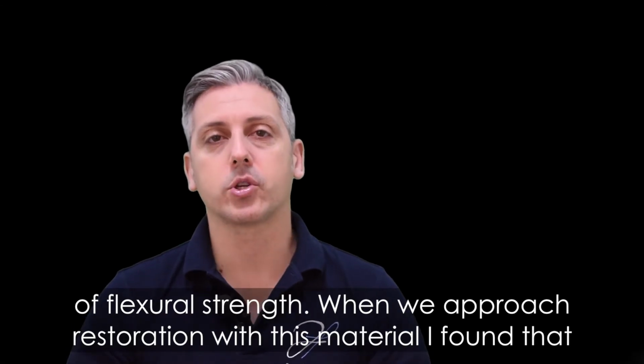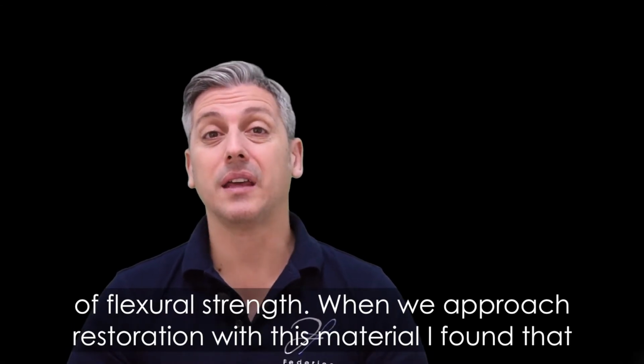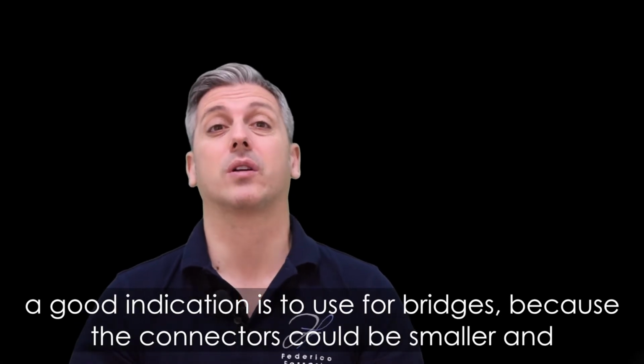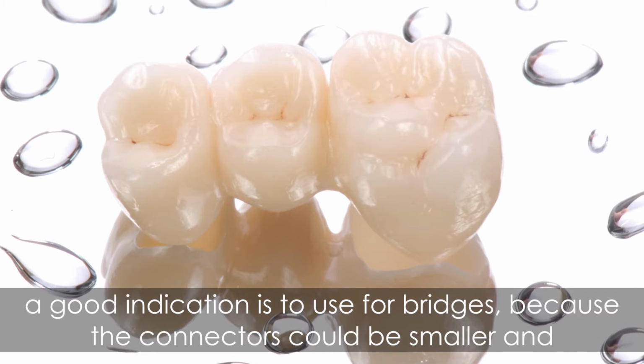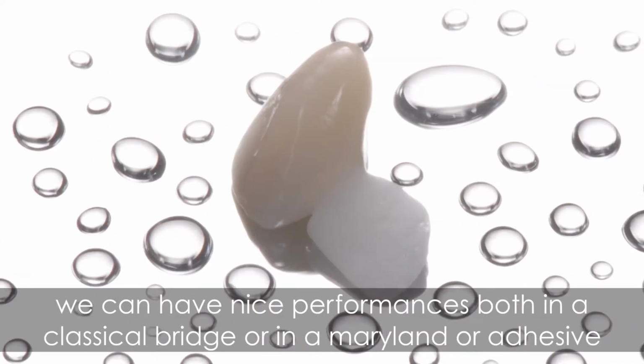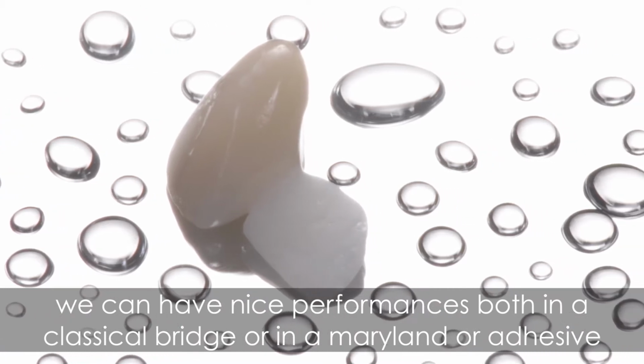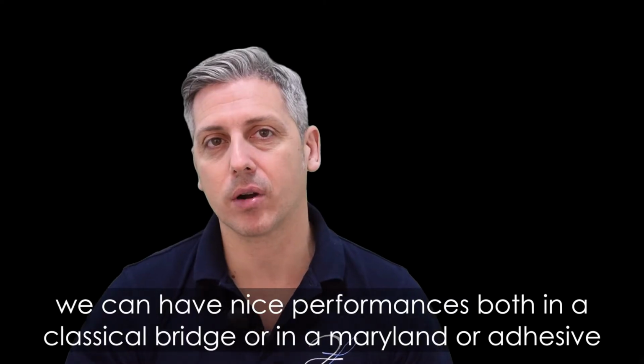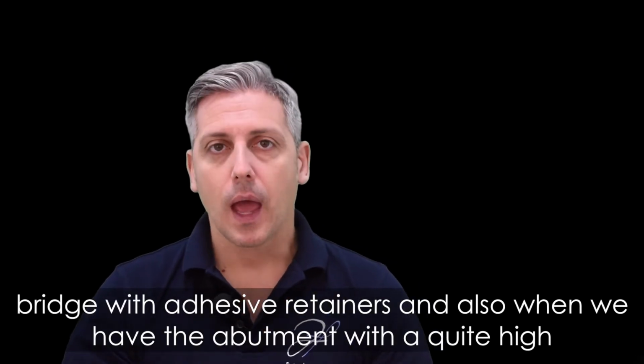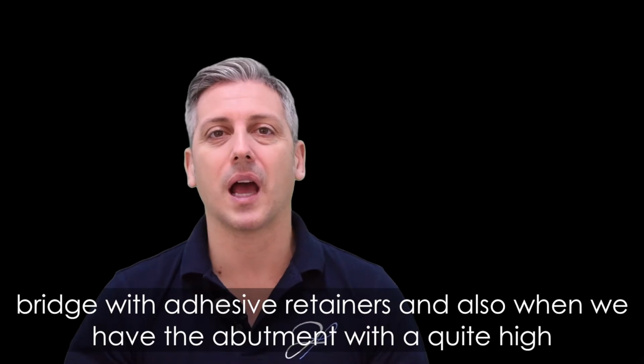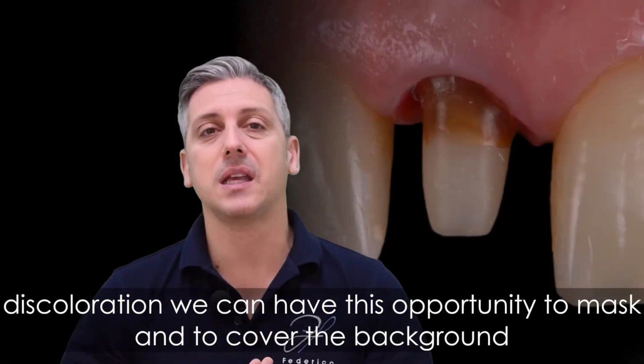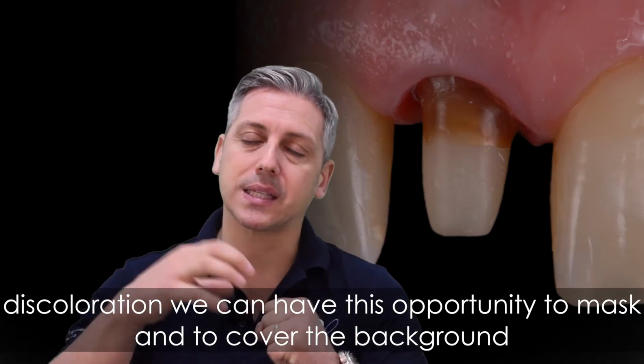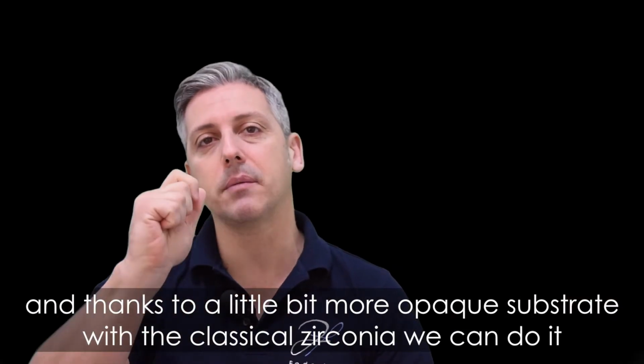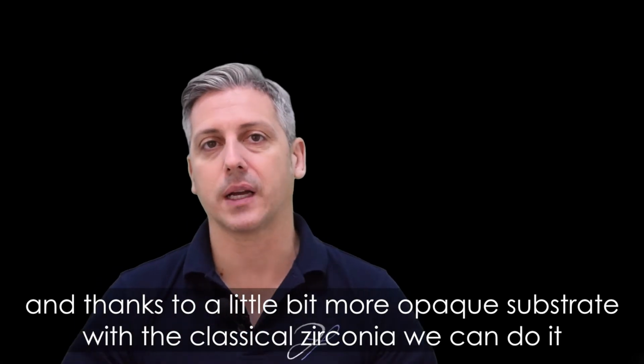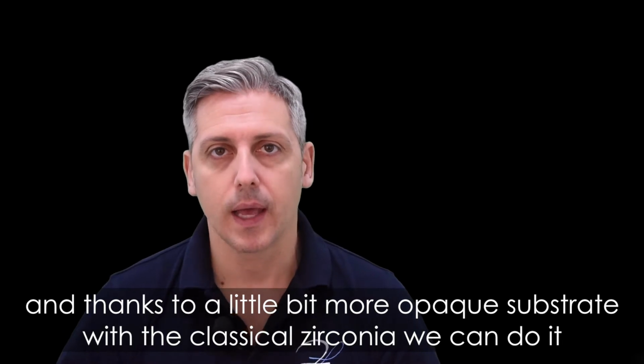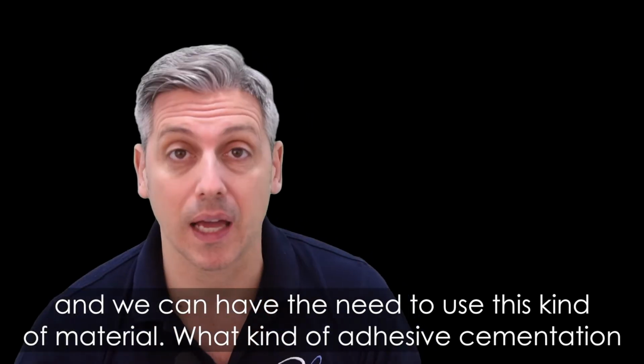When we approach restoration with this material, I found that a good indication is to use it for bridges, because the connectors could be smaller and we can have nice performances, both in a classical bridge or in a Maryland or adhesive bridge with adhesive retainers. Also, when we have an abutment with quite high discoloration, we have the opportunity to mask and cover the background thanks to a little more opaque substrate with classical zirconia.